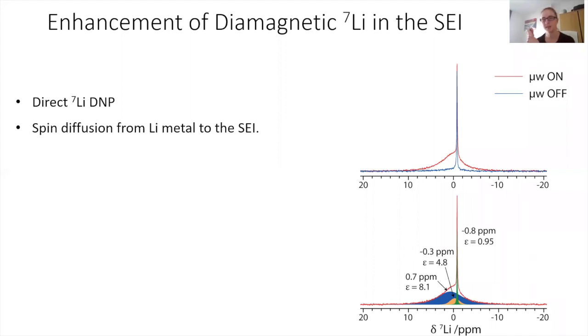And the way we produce these samples is in an actual battery. So we make coin cells where we have lithium chips on either side, and we then charge these cells, and within this process, we form these microstructures on the top of one of these lithium chips, and then we open it up in a glove box and basically scrape off the first layer on the surface of these lithium chips. Then we dilute this with a bit of KBr, pack it in a sapphire rotor generally, and close it off. And then it's airtight enough that we can work with that for a couple of days, probably without seeing too much reaction of the lithium metal with air or anything else.